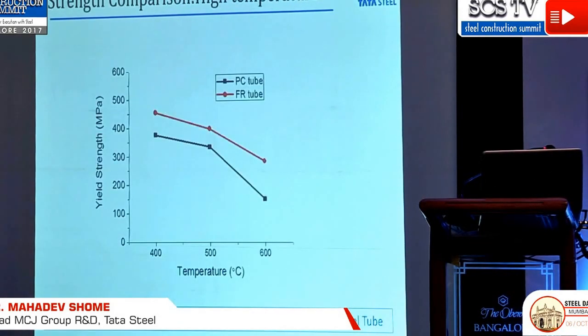This is in case of tubes. The earlier one you saw is for the material that goes into the tubes, and this is for the tubes. The tube properties were much better than 0.5. When we got the figures, if you take the yield ratio, it is better than 0.6. That means it's got better fire resistance properties than the base metal.